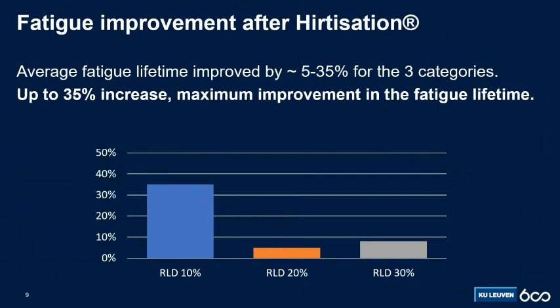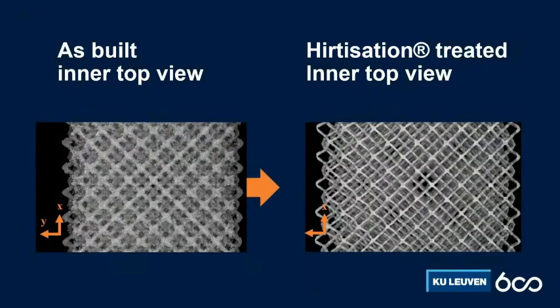This slide shows the fatigue improvement after Hirtisation®, expressed again as a percentage, for the 3 different relative lattice density categories. We can see a span from around 5 to 35% increase in the fatigue lifetime, with a maximum of 35% occurring for the relative lattice density of 10%.